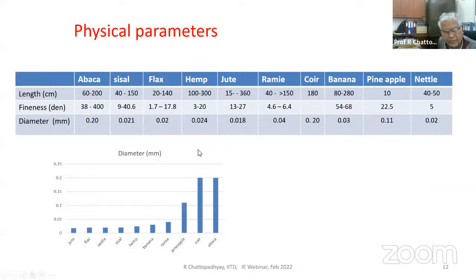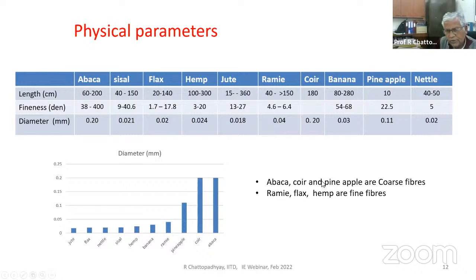Similarly, there are physical parameters like length, fineness, diameter. These values are already available. What we need to see is that the diameters of these fibers have a wide range. Each fiber has a variation in length and fineness and diameters. And between fibers also, there's a lot of variation in their length and fineness. So you can see some fibers which are very coarse, like abaca, coir, pineapple, and some fibers are relatively on the finer side, which is ramie, flax, hemp. They are finer fibers. So nature has given us fibers, some of them very coarse, some of them very fine.